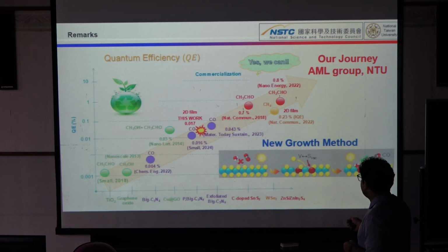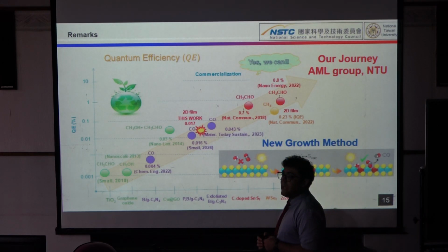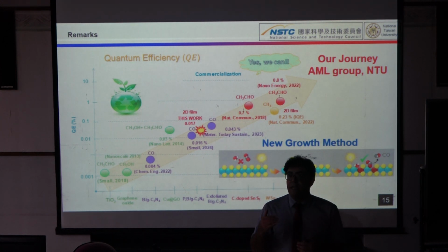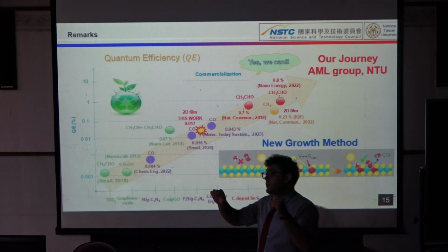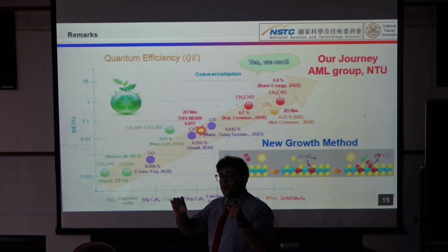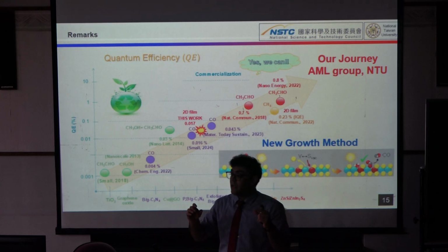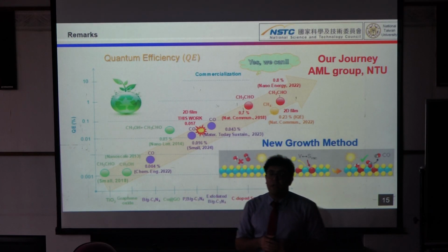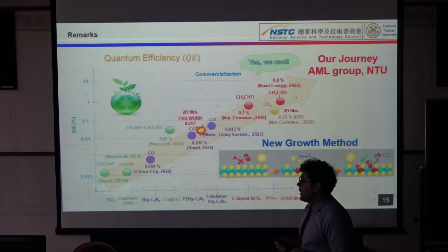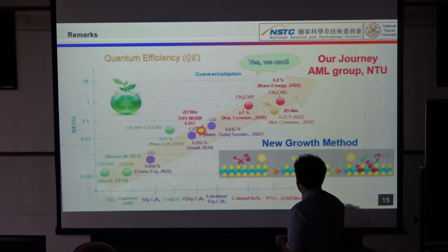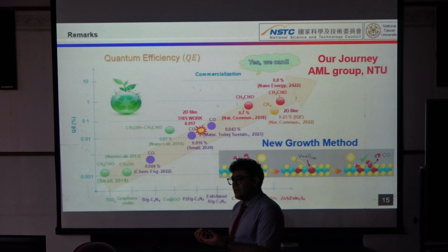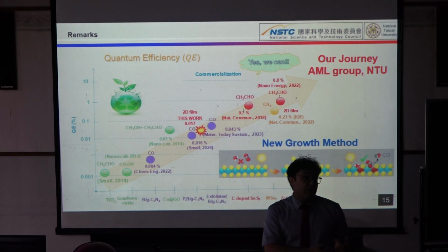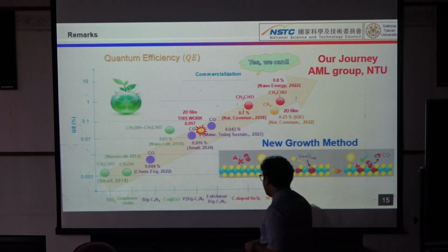Anyway, let me summarize here. I showed you that we can have a method that can help to grow the MoS2 film under the thin SiO2 layer. And that SiO2 layer can be a kind of membrane to pass the sulfur and hydrogen to the liquid under it to grow the perfect MoS2. Also, I showed you that if you have vanadium, an alloy element, and vacancy there, they can help for the better CO2 absorption and even better performance.